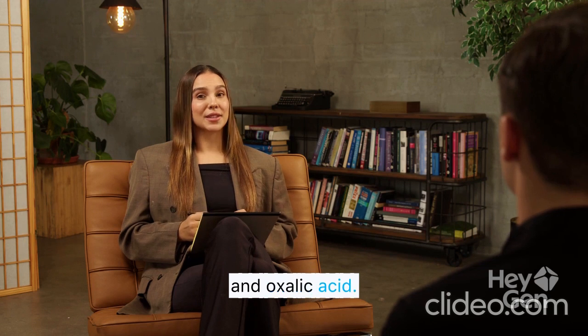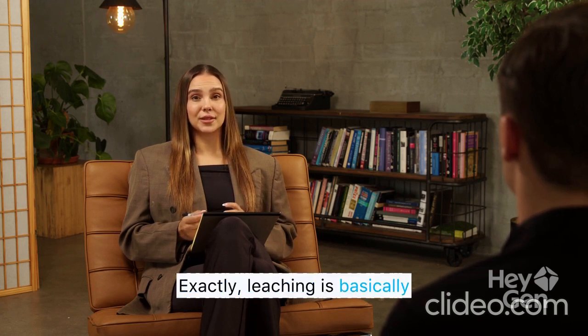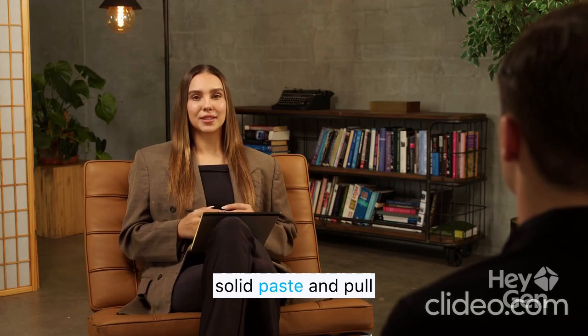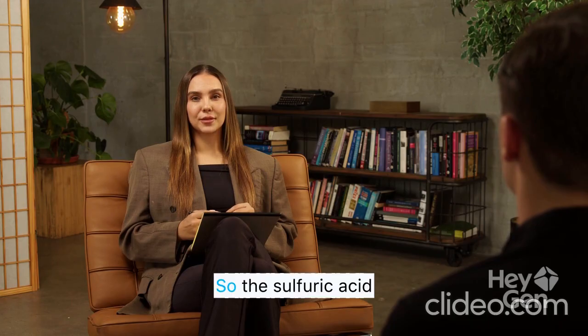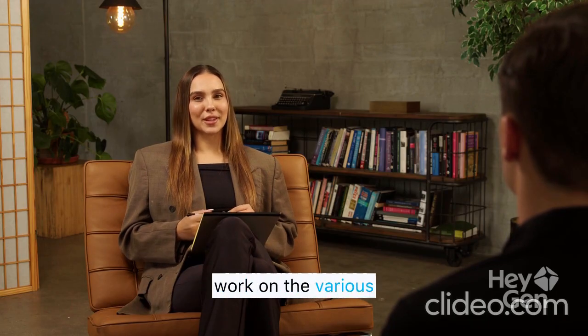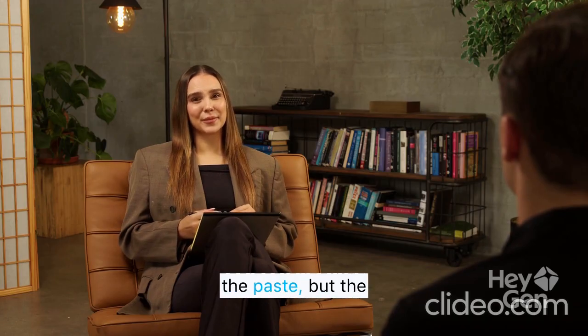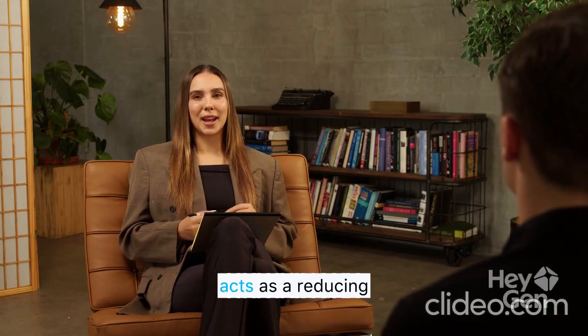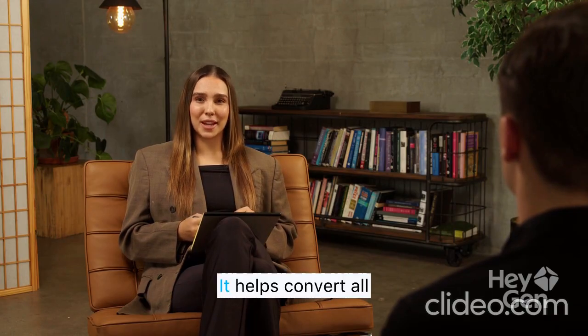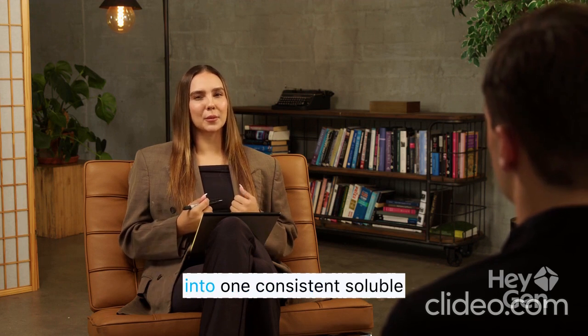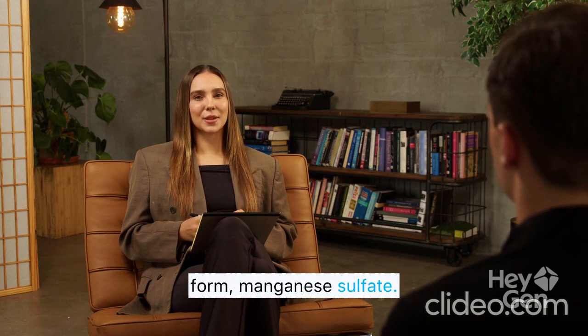So once it's clean, then comes the main part, solution leaching. They use sulfuric acid and oxalic acid. Exactly, leaching is basically using a solvent, in this case the acids, to dissolve the valuable metals out of that solid paste and pull them into a liquid solution. What do the two different acids do? So the sulfuric acid does the main dissolving work on the various manganese oxides left in the paste, but the oxalic acid acts as a reducing agent. It helps convert all those different manganese forms into one consistent soluble form, manganese sulfate. Makes the next step cleaner.